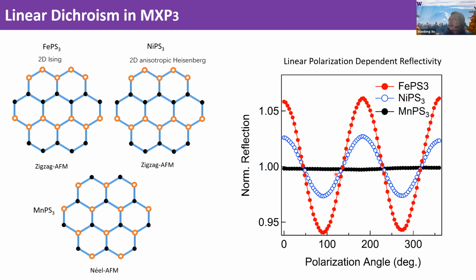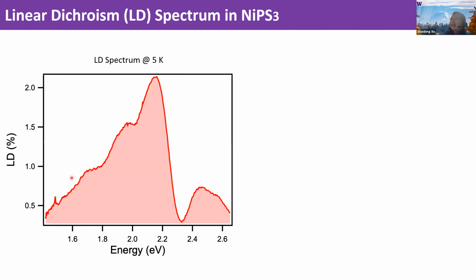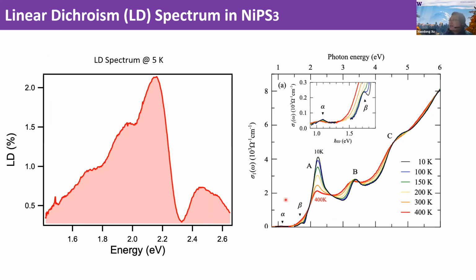Now with this linear dichroism, we can perform spectroscopy. So here I show you linear dichroism measurements as a function of photon energy. And with this measurement, you can see several peaks and wiggles appear. First of all, let's compare with the regular absorption measurements. In the optical conductivity measurement, what you do is shine light onto a sample and then measure reflections. What I show you here is LD. LD is what I measure by sending in vertically polarized light and measuring the reflectivity. Then I also send in horizontally polarized light and measure the reflectivity. Then I take the difference of these two and normalize by the sum. This gives my linear dichroism measurement.